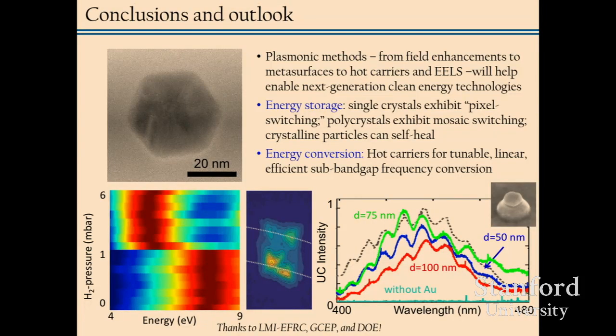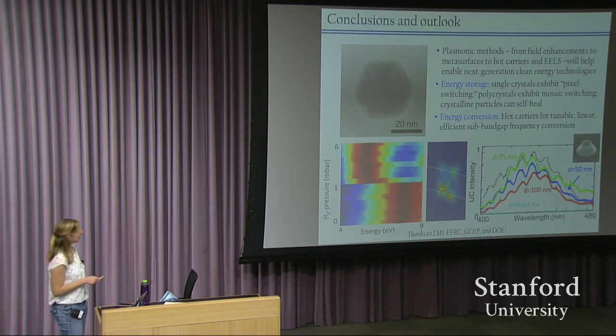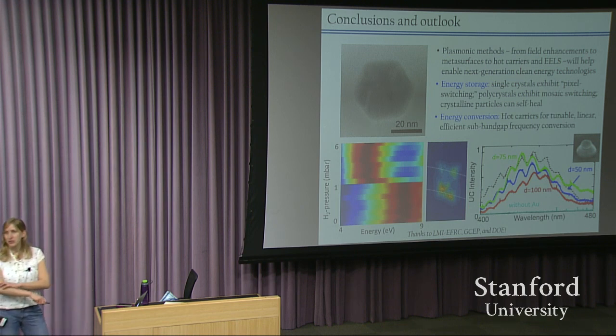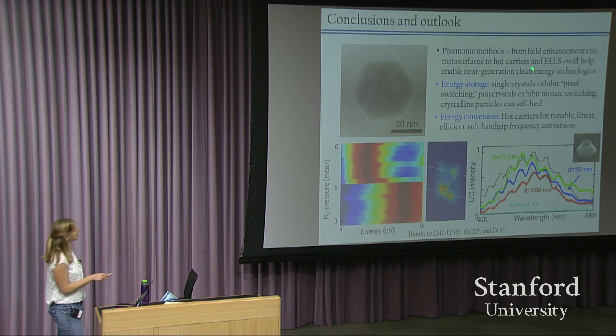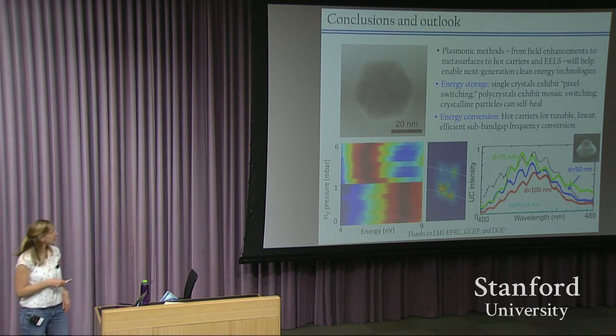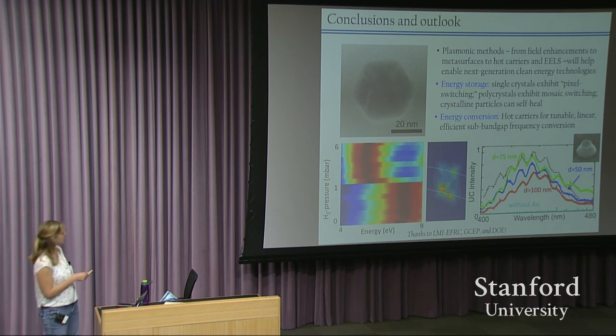In summary, first of all, hopefully I've shown you that plasmonic methods, from various field enhancements and metasurfaces to hot carriers, can help enable next generation clean energy technologies. My particular work has focused on how plasmonic methods can allow us to better visualize some of these energy storage devices. And what we found in looking at a relatively simple and straightforward system that has many parallels to lithium ion batteries is that single crystalline nanoparticles tend to exhibit this pixel switching, where they're either in one phase or another, but they don't coexist in equilibrium, whereas these polycrystals exhibit mosaic switching, where parts of the nanoparticle don't transform to the new phase. And also, I've shown you that these single crystalline nanoparticles can self-heal.